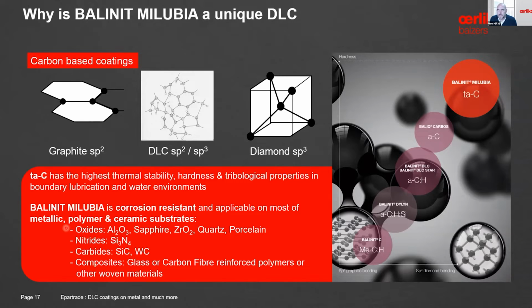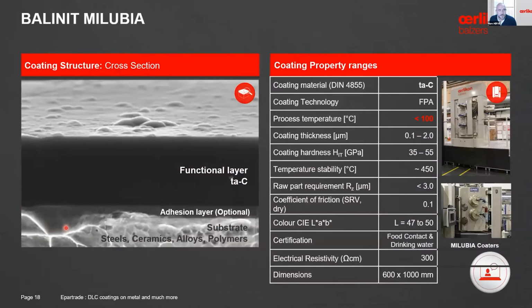But at the time, we really thought, can we do something else? Can we apply the coating on elastomer? So when we thought about it, the first question was, okay, if we had to coat an elastomer, what could be the blocking point in putting a coating on this kind of substrate? So first, it is a non-conductive substrate, but with this technology, we have an answer. The other thing is, as I said at the very beginning, most of the coatings are made at pretty high temperature, 250 degrees and higher.